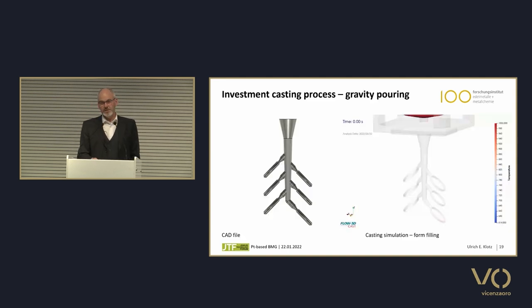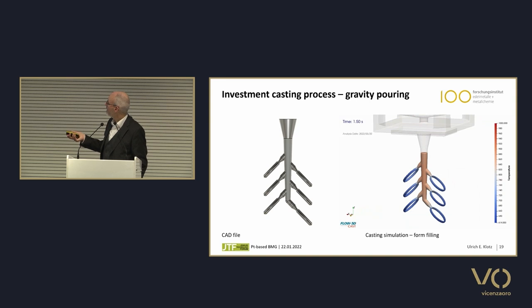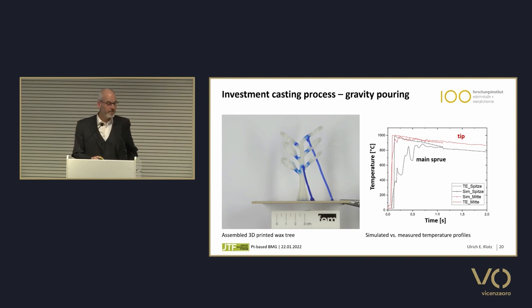So then we did a gravity pouring simulation. Could you also please play this video? We see the melt is pouring, and filling takes longer. And you see all the gas bubbles coming up, and it takes about 1.1 seconds until the melt becomes stable. Then, the same result for this tree, we also see quite good agreement between the thermocouples and the simulation.